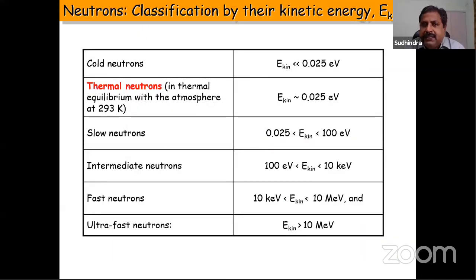Now, depending upon the kinetic energy of neutrons, neutrons are classified into different varieties, like cold neutrons, thermal neutrons, slow neutrons, fast neutrons, ultra-fast neutrons. What we require for neutron diffraction is thermal neutrons with an energy of about 25 meV. If you convert it in terms of wavelength, you will find that the wavelength you get from thermal neutrons is of the order of 1 to 5 angstroms, which is actually ideal for diffraction purposes. So that is why when we do neutron diffraction, we are always talking about thermal neutrons.